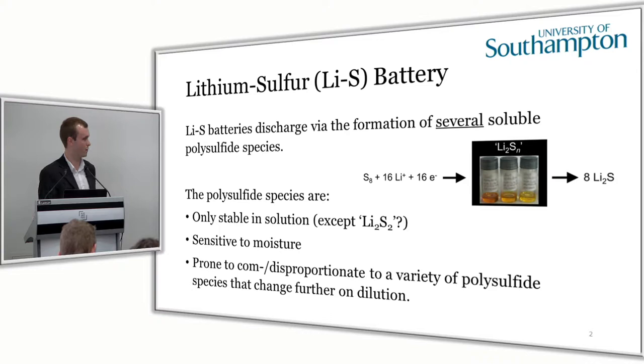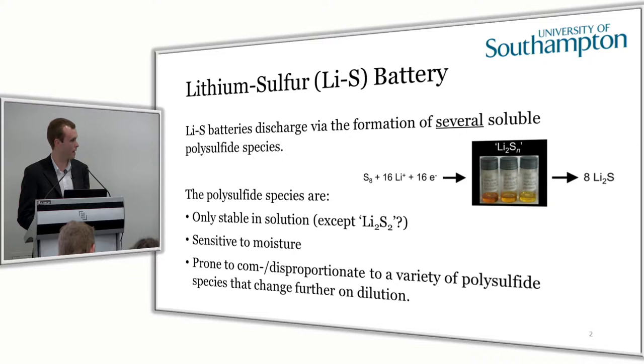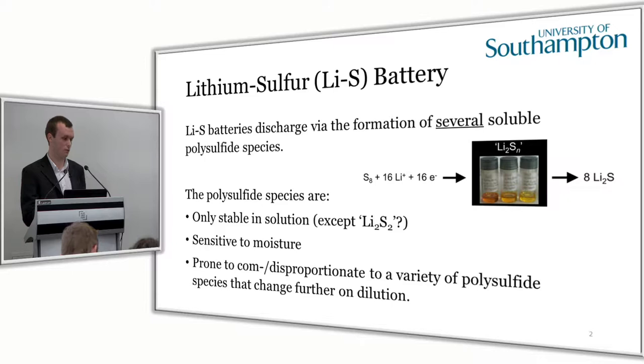These polysulfide species appear to be only stable in solution, except for maybe Li2S2. They're sensitive to moisture, so we have to analyze them under inert conditions, otherwise we'll get H2S, which is not something we want. They're also prone to comproportionation and disproportionation. So even if you were able to isolate or synthesize just one of these polysulfide species, it would quickly disproportionate to a variety of polysulfide species at a thermodynamic equilibrium of the lowest energy.